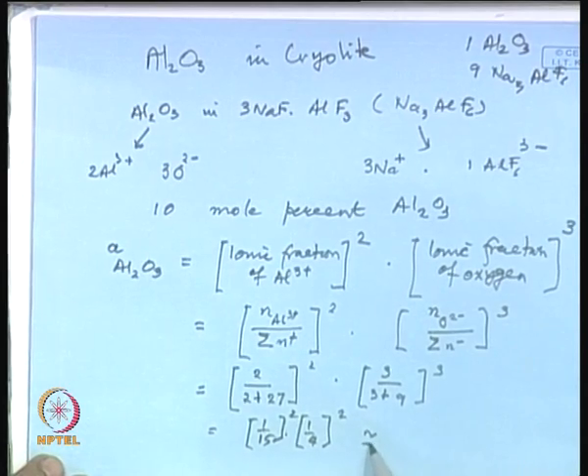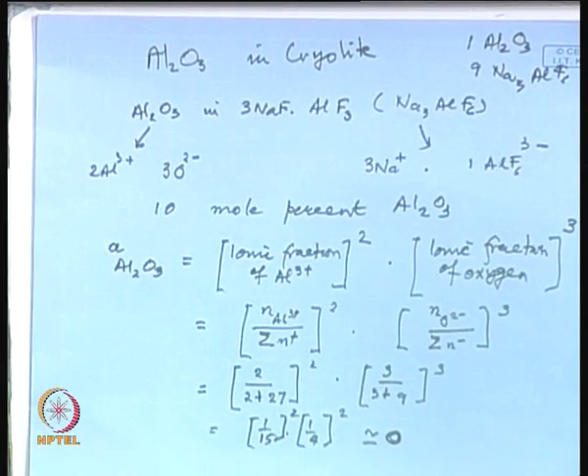This is very, very small. So, there we had said that for an ideal solution 15 mole percent means 0.15, therefore, activity is 0.15. That is not true. According to Temkin's equation, this assumption is not valid. So, we said if the solution is ideal, the activity of alumina is equal to mole fraction 0.15, it is not true. This actually should be practically very small, it cannot be 0.15.